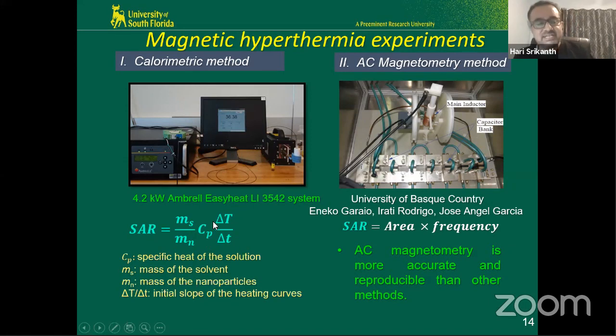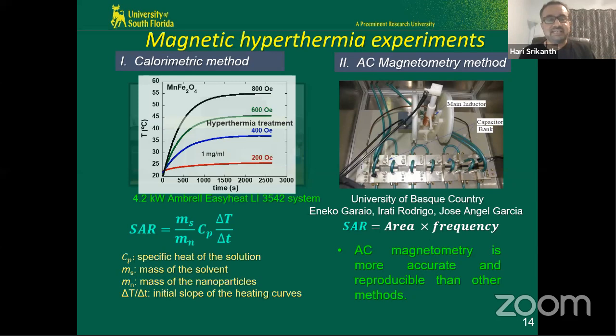Remember that you need to increase the temperature to about 40 to 45 degrees Celsius and hopefully stop there. You don't need to overheat, right? And if you don't apply the right conditions, you will never get to the temperature. So this is what we need to monitor here in the calorimetric method. Our data looks like that. As you can imagine, that's the hyperthermia window, 40 to 45. We need to get there as quickly as possible, right?